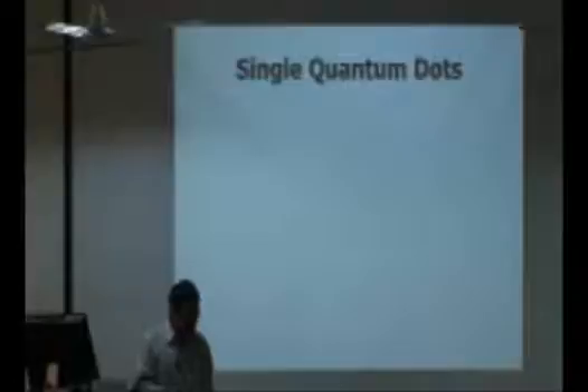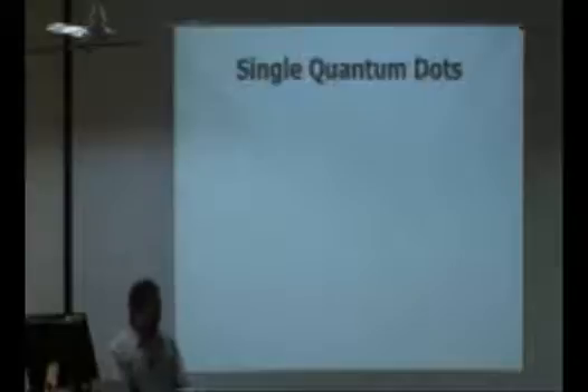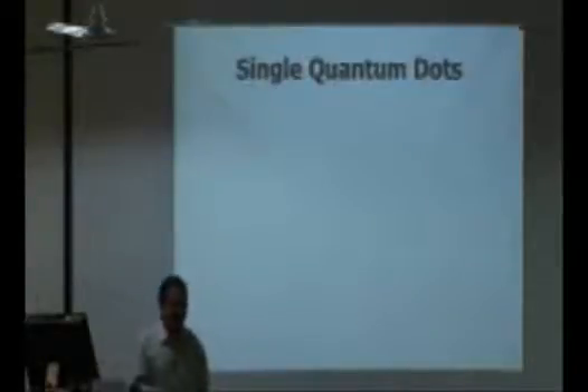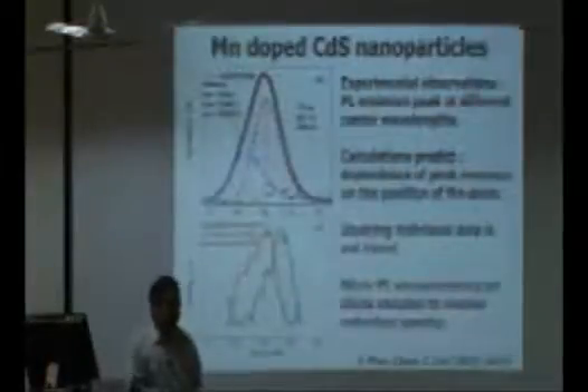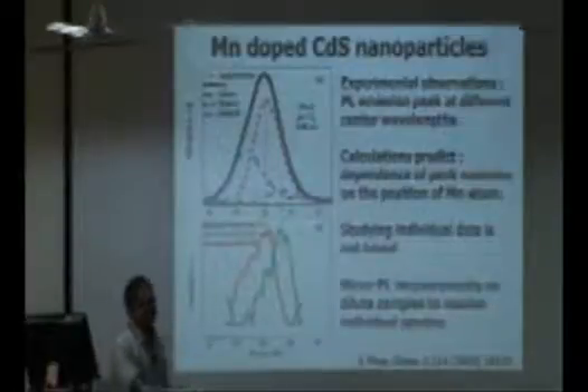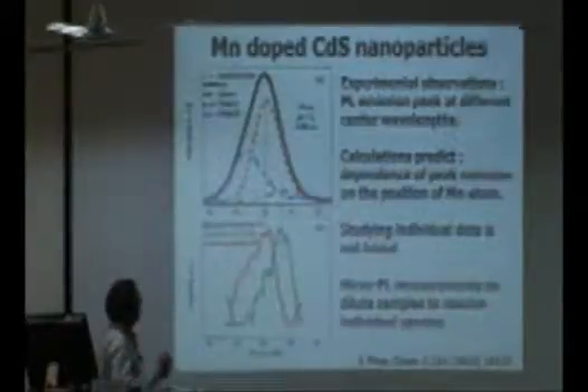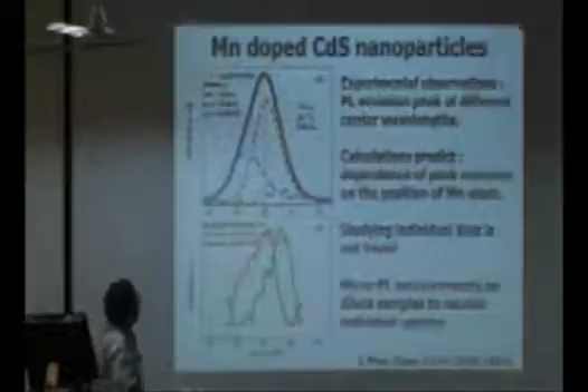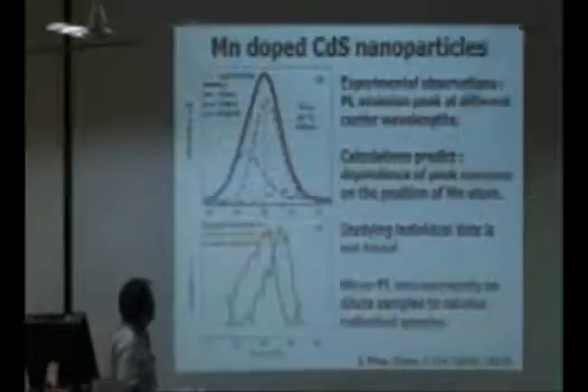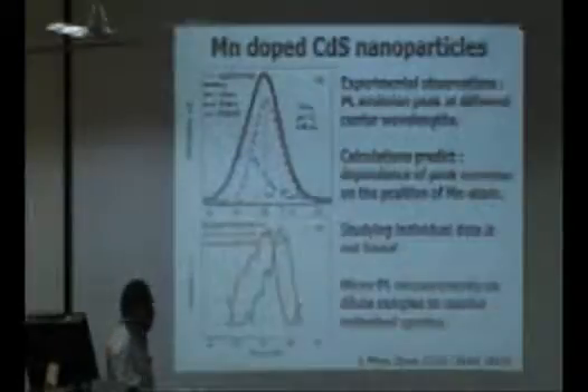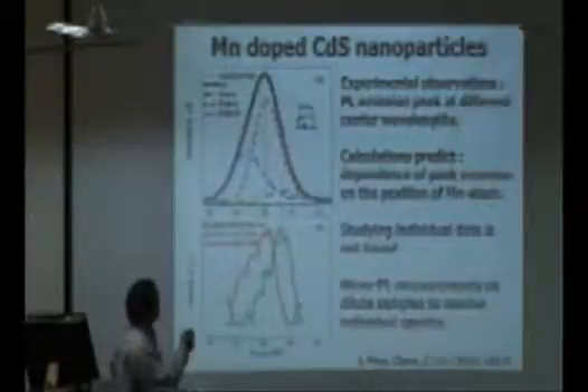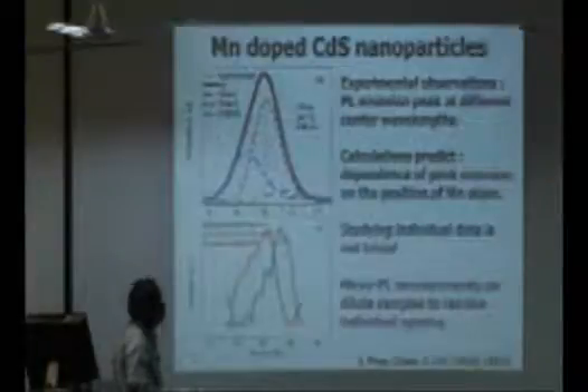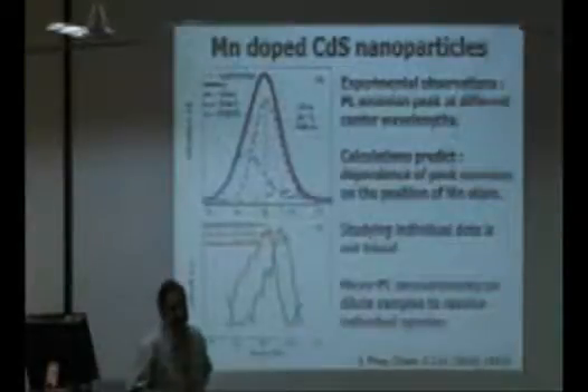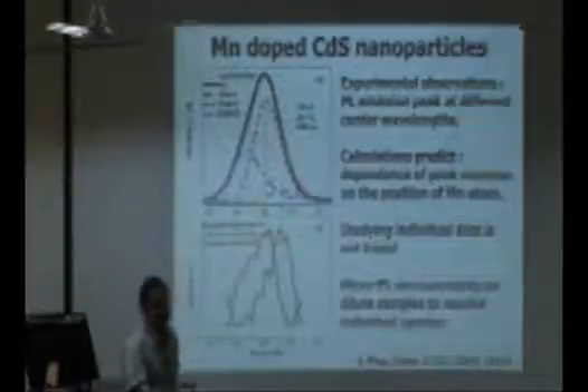Just to summarize some of our recent results on single quantum dots: Professor Ray mentioned in the morning that quantum dots are very useful for electronic light emitting applications and light detection systems. One of the questions is, can we get efficient green emitters? One candidate for this is manganese doped cadmium sulfide nanoparticles or quantum dots. But the issue here from a basic physics point of view is that different groups have reported different center peak positions for this luminescence peak. The question was what is causing this wide shift in reported values of the central peak.